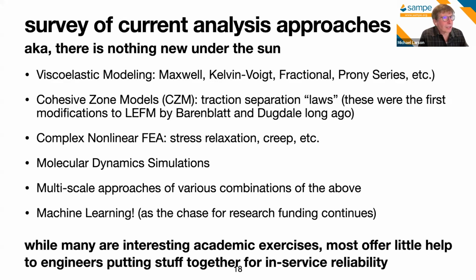These cohesive zone models that I mentioned, where we have a set of pseudo laws to replicate what's happening in our adhesive, are called traction separation laws. I put the quotes. Usually the laws don't have quotes. They're not laws. They're usually gotten from an experiment, and then we infer something, and it's a case-by-case basis. People have employed nonlinear finite element analysis, which, depending upon which code you're using, can involve a lot of ill-defined constants that a user would have to employ.